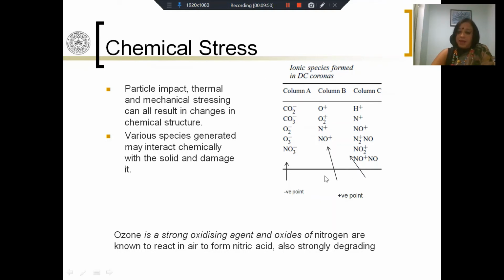All these different types of species might be formed, and some of these species may not be very good for the material from which they have been generated. So, for example, ozone. Ozone might be created when you have a negatively charged electrode at very high voltages. In that case, you have to remember that ozone is a very strong oxidizing agent. Let's say you have air and ozone is created, and this O3 reacts with the oxygen and the nitrogen that is present in the air, and it will produce oxides of nitrogen. Oxides of nitrogen are known to react in air to form nitric acid, and nitric acid is strongly degrading, strongly corrosive to the material around it. So what is happening in chemical stresses? Various kinds of chemical reactions might take place such that the material that you start with, you end up with a different material.